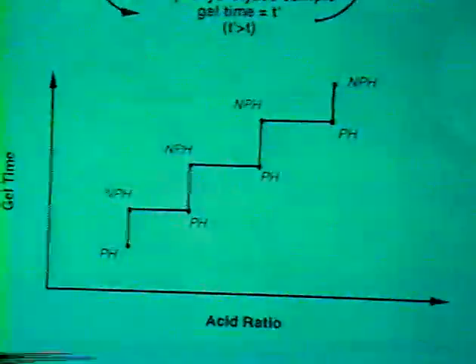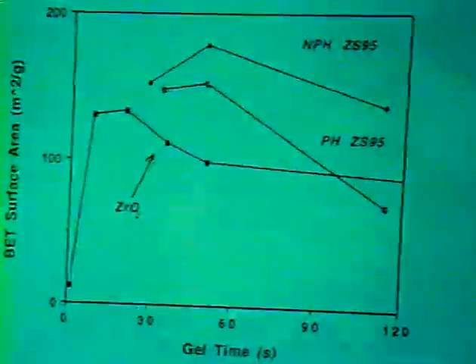For a specific combination of zirconia and silica, we first determine the gel time for a prehydrolyzed sample. We then remove the prehydrolysis while keeping all the other conditions the same, and allow the gel time to go to whatever value it is. In this case, it's T prime, which is longer than the gel time with prehydrolysis. We add the prehydrolysis back on, and then use acid as a tuning variable to bring the gel time back to the same value. The best way to appreciate this is the bottom graph, in which we are looking at the gel time as a function of acid ratio, and this is what we refer to as a stair-step synthesis. In other words, at a specific acid ratio, we vary the gel time by taking out the prehydrolysis step, and then at each constant gel time, we vary the acid ratio in order to compare the prehydrolyzed versus non-prehydrolyzed samples. Now,